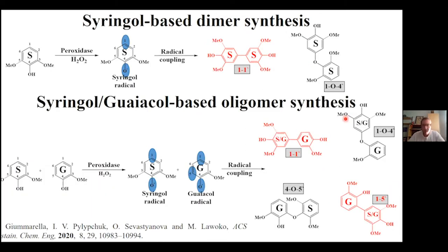With the same aim, we adopted a similar strategy using different compositions of the monomeric substrates to now study the structure of eucalyptus Kraft lignin, which is the main focus of this presentation. For matter of time, also, when Syringol polymerized, or Syringol in presence of Guaiacol, we got, according to NMR characterization, the presence of only structures with carbon-carbon direct linkage. But let's see how we got this information.